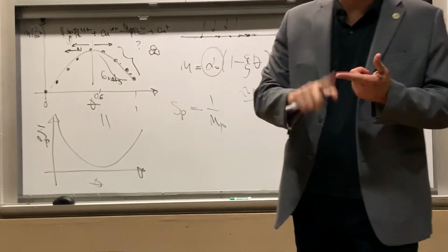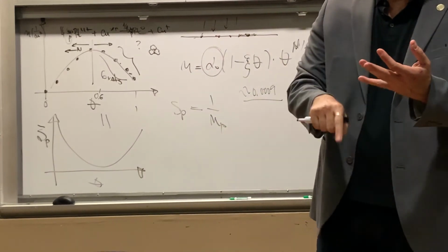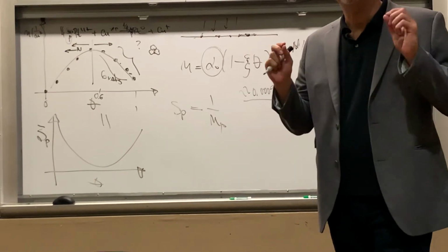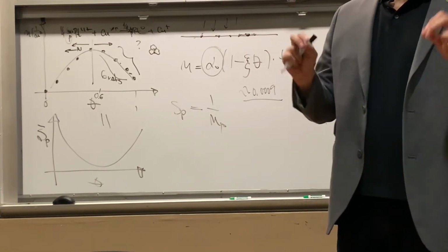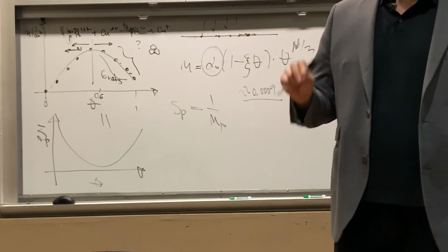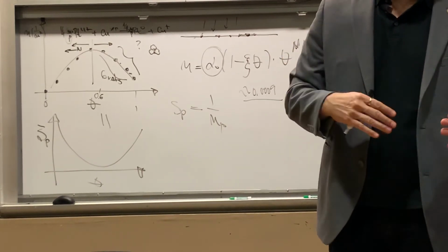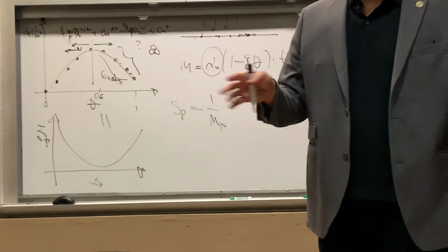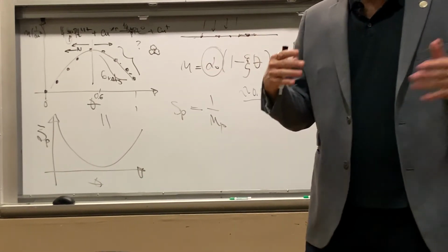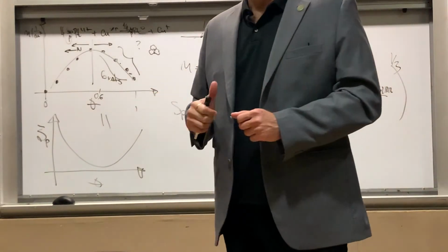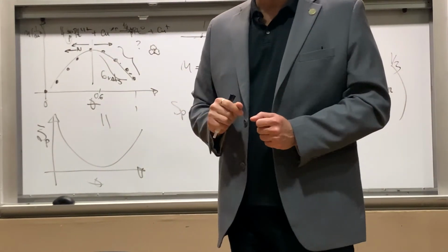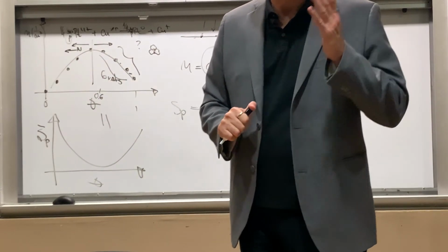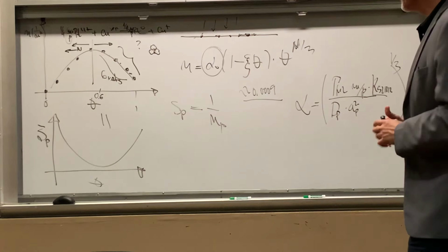Copper could be stabilized in copper plus or copper 2 plus, platinum could be plus 2 or plus 4. Based on that, you can play with this and figure out that you're not always getting the same type of catalyst because the clusters are not the same. And that's what happens to me Monday versus Wednesday. Monday, I don't even look, I make platinum solution, platinum 4, whatever. Wednesday, I become a little bit more prudent and I make it from platinum 2 plus. Suddenly, wow, two different catalysts. Just by controlling the chemistry, because you control n.